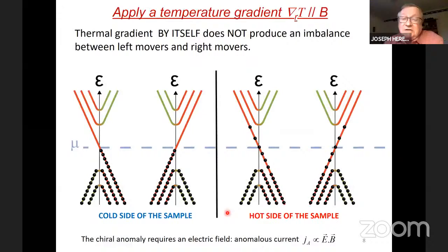So what happens with this thermal field? If we put in a temperature gradient, it is not, of course, applied in k-space, it's applied in real space. So we have the hot side of the sample, where we have a softer Fermi distribution at both Weyl points. And we have the cold side of the sample, where we have a sharper distribution on both Weyl points. So you see here, in principle, there's no change in delta N, and that's what the equation above illustrates.